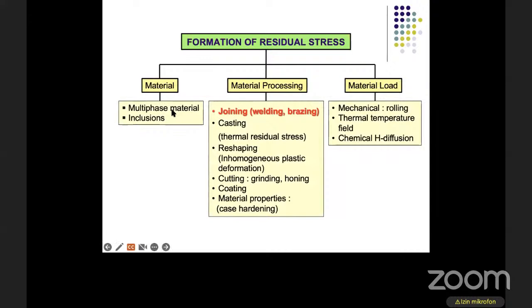If we look at residual stress here, we can see that residual stress can be divided into 3 groups based on the cause of residual stress. First, residual stress can be created by materials such as multi-phase material inclusion, and also can result from material processing, especially joining, welding, and brazing, and also material loads such as rolling and thermal temperature field, and also hydrogen diffusion.